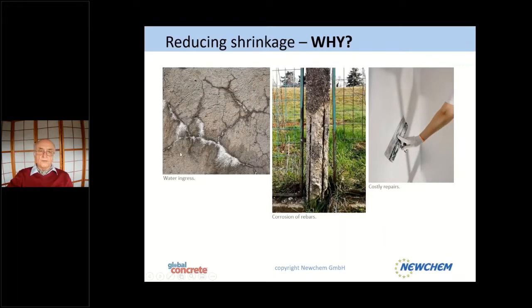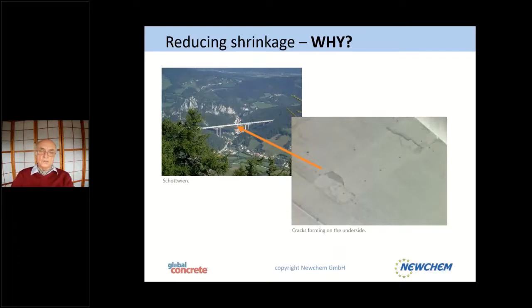Here, the same thing. When you have concrete, you have a water ingress, or you have efflorescence on the other side. If you use steel in your construction and you get cracks, then the water will go in, and with time, the iron will start to oxidize, expand, and you will break your construction. That ends up with costly repairs. One example from Austria: we constructed a bridge here, and after almost finishing the construction, cracks formed underneath the bridge. Big lumps of concrete fell down into the valley. We are very happy that nobody was hurt, but you can see what effect cracks may have in nature.